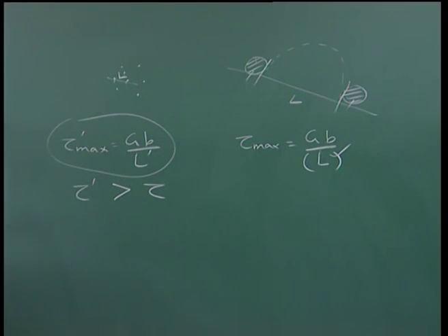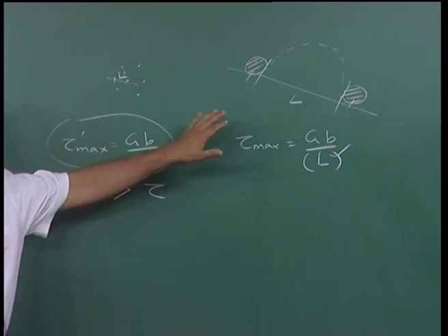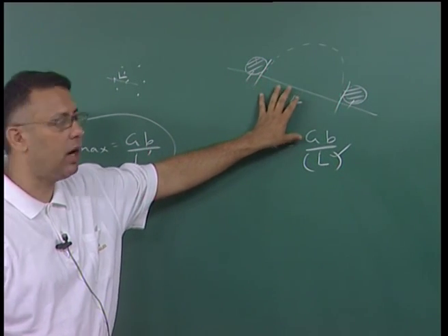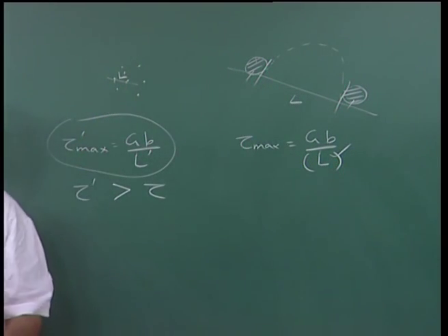That means a higher shear strength as compared to just motion of dislocations in an unimpeded matrix. Therefore, if I have precipitates which are far apart and coarse, they give lesser hardening as compared to a fine distribution of precipitates. Now, how do I obtain a fine distribution of precipitates is the reason we are considering this phase diagram.